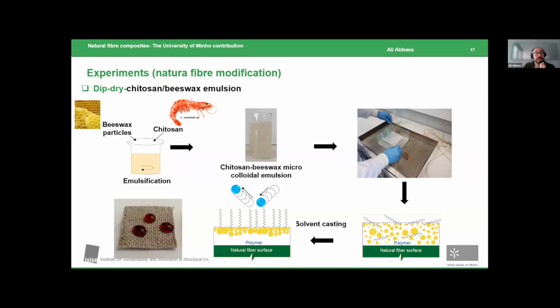So moving to the second protocol, which is the dip dry. The dip dry technically comprises a polymeric formulation reinforced with a substance of choice. In this case, we chose chitosan as a bio-based polymer. So this protocol is 100% bio-based. Chitosan, for those who don't know, is a bio-based polymer derived from crustaceans, shrimp-like biomarine mass, and it's very sticky. It can stick on lignocellulosic surfaces in acidic medium.